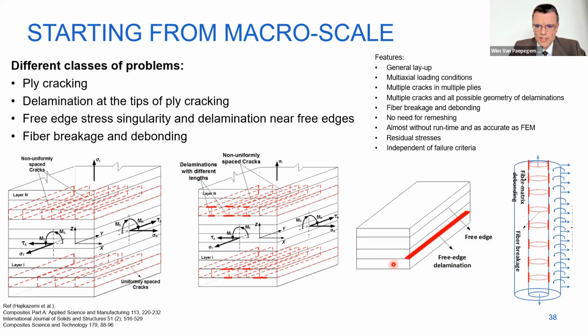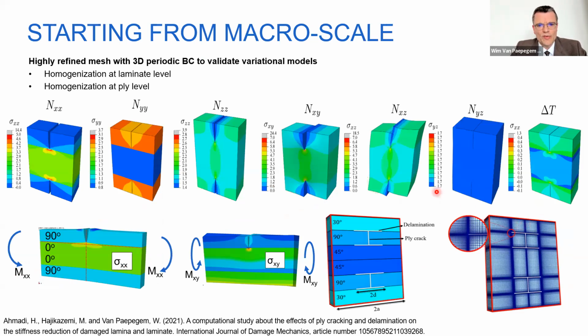And we can also do that for a free edge delamination. And this is more on micro scale again, where you have a fiber which is fractured and the shear lag layer which is related to it. We can then also introduce residual thermal stresses. And of course, maybe you have a hard time believing this is possible. We also have a bit of necessary doubt, and we first want to validate this. So we built a lot of finite element models, which are only meant for verification and validation of our models. And here you see all the typical loading conditions in classical laminate plate theory. Also here you see the bending moments and twisting moments that are applied.